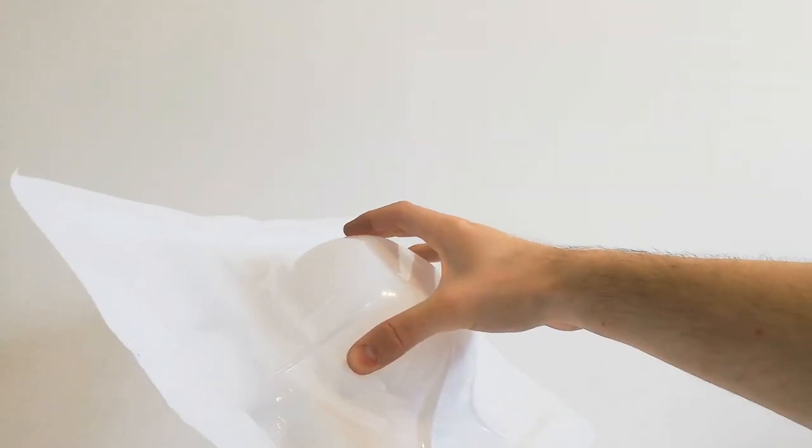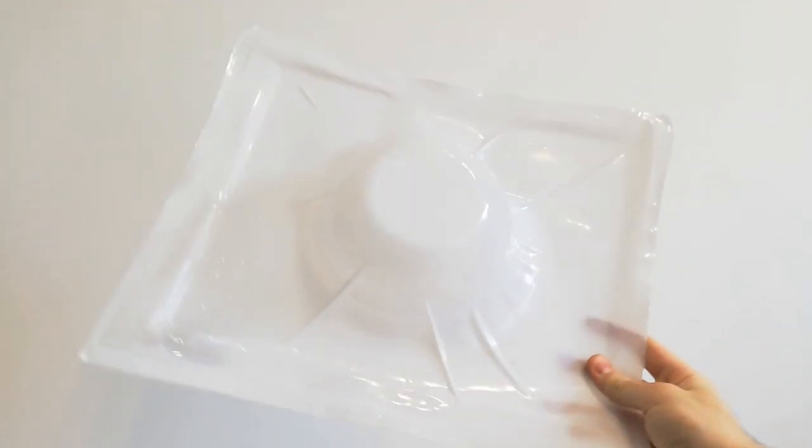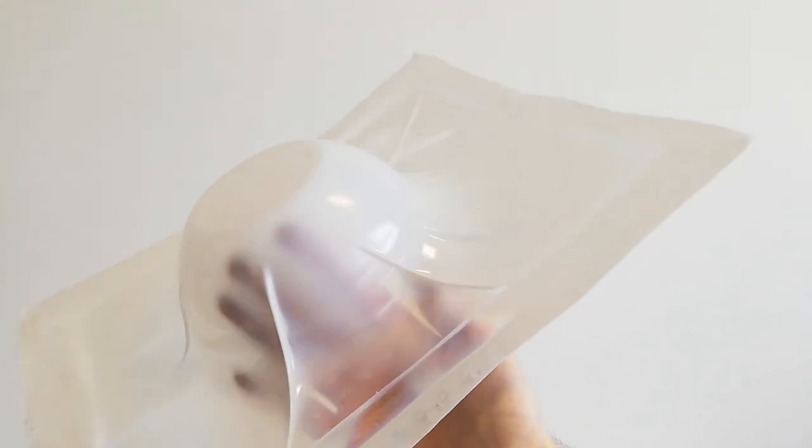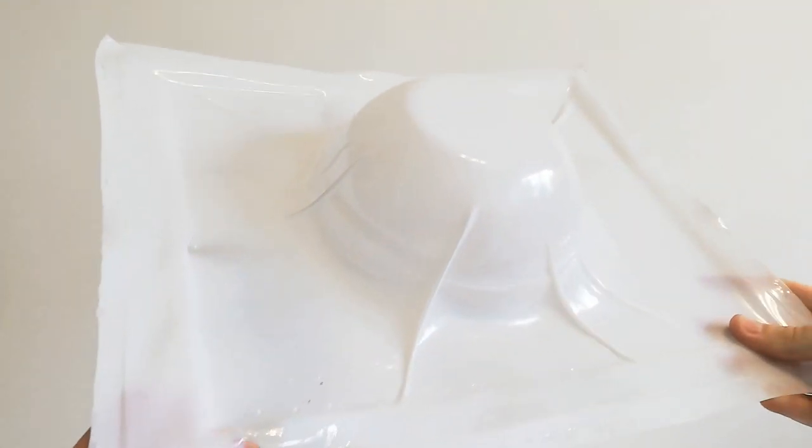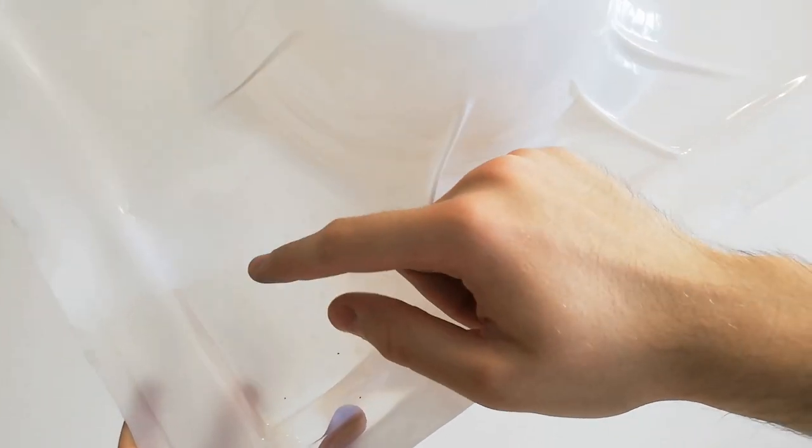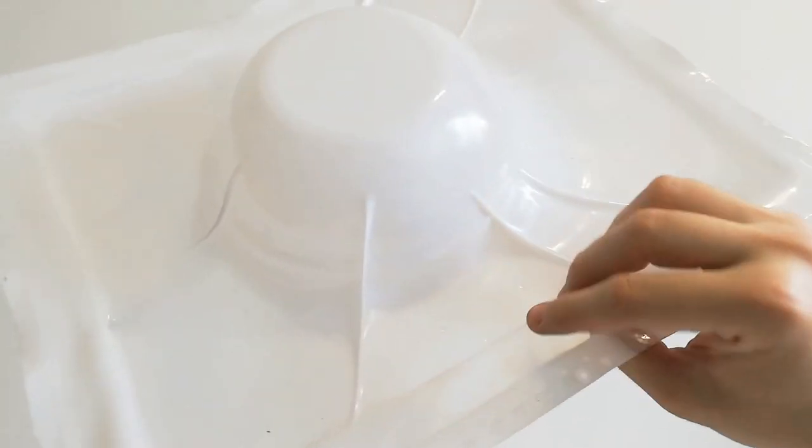Due to the geometry of the back, it was also really easy to separate the visor from the form. One important note on the vacuum forming plastic though. During the first material trials, instead of PETG, I was trying to use the regular PET. I wasn't able to get good parts out of it though. Due to a slight chemical difference, a normal PET first melts in the oven, and then immediately crystallizes. The crystallized PET turns milky white, and it becomes too hard for the vacuum form. As you can see, this resulted in severe wrinkling, and of course you cannot see anything through it at all. Stick to the PETG.